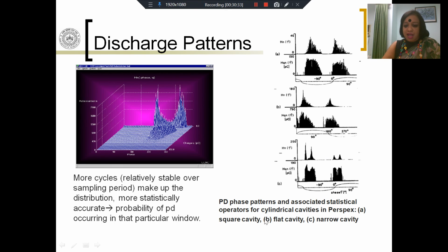These are 2D patterns. These are again taken from a paper which is in the public domain. What you can see is these are PD phase patterns for cylindrical cavities in perspex, and depending upon the shape of the cavity, you get a completely different PD pattern shape. The pattern looks completely different when you just visually look at it. The first two are for a square cavity, these two are for a flat cavity, and these two are for a narrow cavity. Narrow cavity means a long cavity, where the width is low and the length is more. At the top are the phi's, and these are the Q and N. And as you can see, they are quite different even at a look.